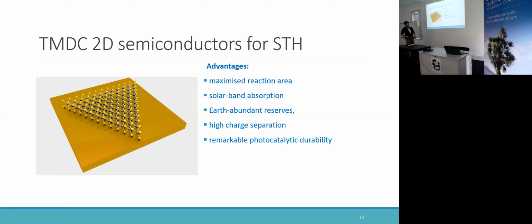And also, it has solar band light absorption, basically ranging from visible to near infrared. And the raw materials to produce these 2D semiconductors are earth abundant. These materials also don't have dangling bonds in the third direction, which means they have very high charge separation ability. And they have very good photocatalytic durability. For years, I don't know, but for months, I'm pretty sure there were experiments proving that these materials can run for months.